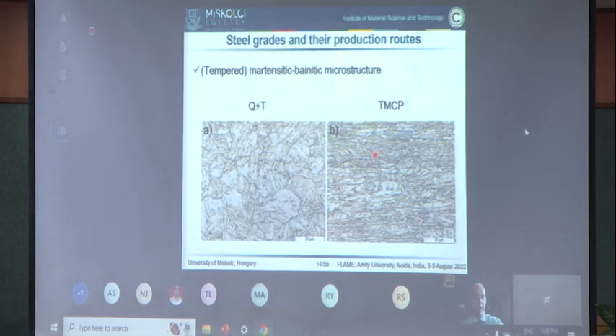Here you can see a typical microstructure of quenched and tempered high-strength steel. You can see it at the left-hand side. And at the right-hand side, you can see a typical microstructure of thermomechanically rolled high-strength steel. Both microstructures have a fine-grained structure, but the grains are even finer in TMCP steel. In TMCP steel, the grain size in some cases is just some microns.